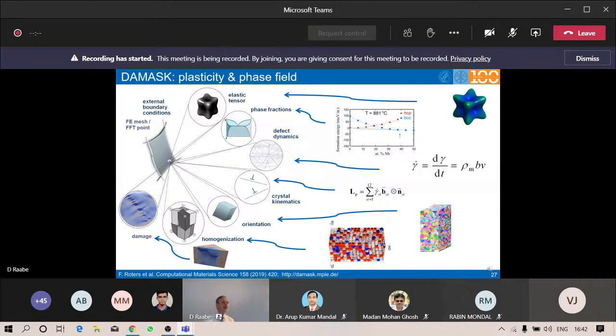Because maybe the biggest challenge that we currently encounter in such simulations is how to predict also the gradual evolution of microstructure-related damage in such materials with their high degree of inhomogeneity. So that gives you just a rough impression of how the setting in DAMASK works, on which constitutive parameters have to be taken into account. That means you can retrieve the information that you need to map here, either from microtexture measurements or from X-ray texture measurements, and subsequently decompose it.